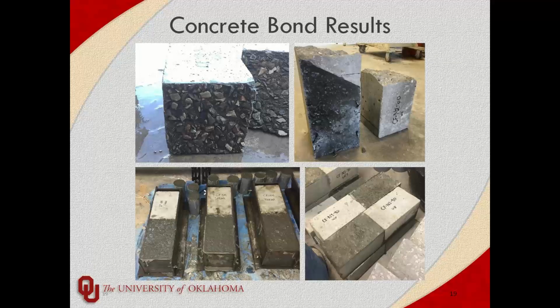And then the last of what I call small scale tests is we did the concrete bond strength tests. We did a typical mimic of the modulus of rupture test, where we cast half with conventional concrete, let it cure for at least 28 days, and then we would pour UHPC against it. And we varied the angle of the interface as well as the surface condition of the interface. On the upper left of this, we did an exposed aggregate finish. We put a retarder on the form surface and sprayed it off to get some of that paste. And then we also did sandblasted, unclean, or just cut, and then wire brushed.